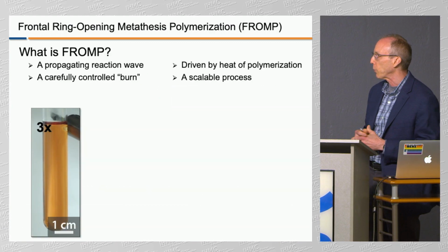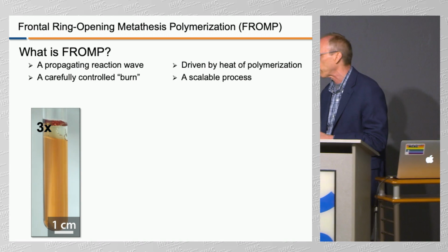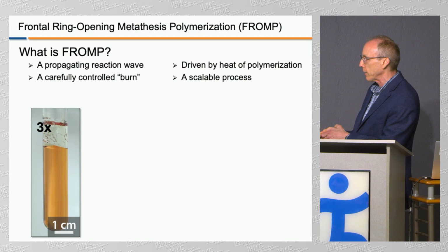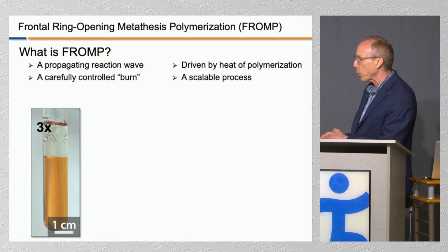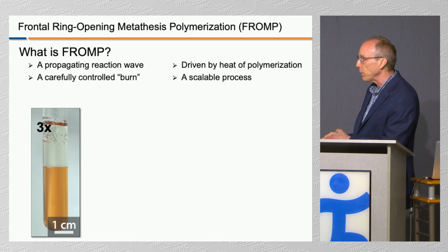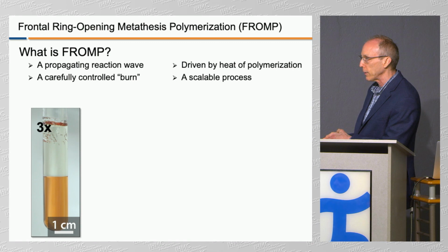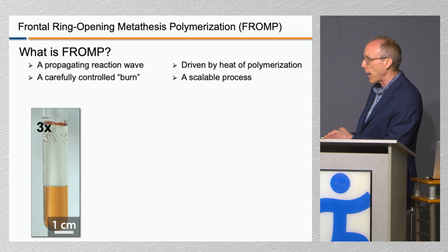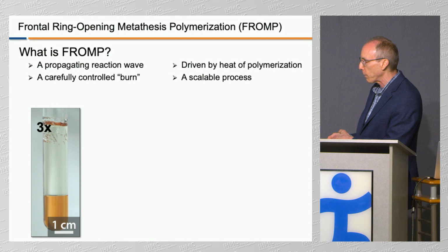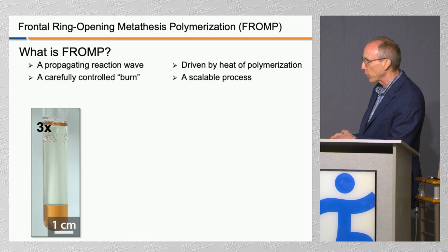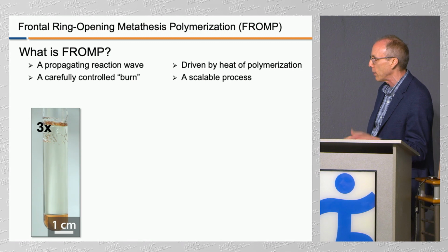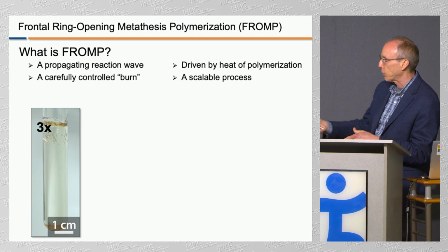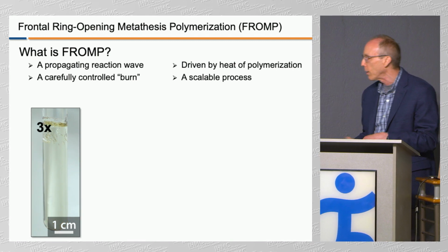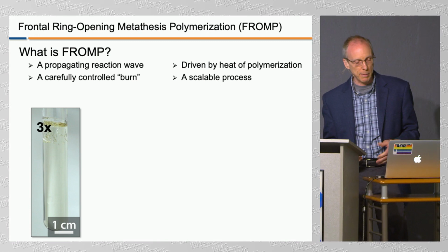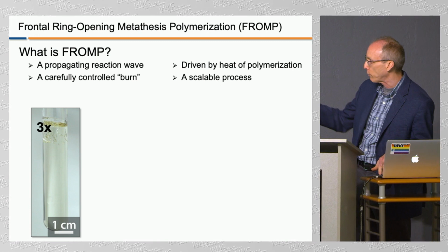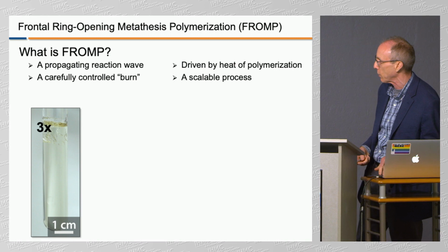And here's FROMP. So right away, you'll get a chance to see what FROMP is. Notice there was a soldering iron touch at the very beginning. This is liquid. It's the raw material. It's colored orange because of a catalyst that I'll show you in a second. This is now hot, very hot. This is cool, room temperature. This is the front that's moving through at a very nice, controlled, steady rate. And this is sped up 3 times, so it's a little bit fast. But actually, we have samples right now that will go faster in real time than what that movie did.